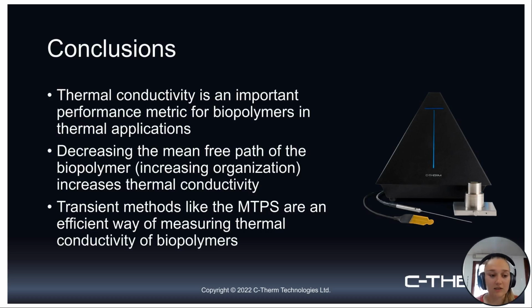And just a couple of quick conclusions. As I mentioned, I don't want to go into too much detail as we've done a lot of work in this in the past and have many webinars and papers available if you'd like to take a deeper look at this. But just to conclude, thermal conductivity is a very important performance metric for biopolymers and thermal applications, in addition to the other thermal analysis instruments we talked about earlier, the DSC, STA, and TMA. One way to increase the thermal conductivity is decreasing the mean free path, or in other words, increasing the organization of the polymer. And finally, the transient methods like the MTPS method are a very efficient way of measuring the thermal conductivity of the biopolymers. So that's going to be it for thermal conductivity here, and I will just share the final outro slides as we approach the Q&A here.